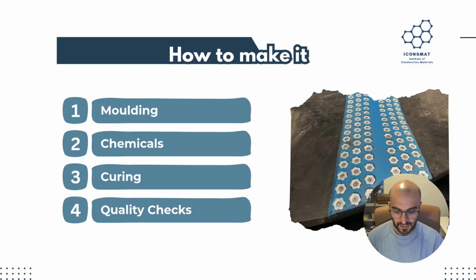Some polyurethane samples, especially the one that I've used, started to generate CO2 gas, and because of the viscosity levels of that liquid, that generated gas was entrapped inside the sample, resulting in a lower tensile strength. So, ideally, we want to have a vacuum chamber where the curing happens. There are other notes in the scientific papers where heat curing is recommended because it improves the mechanical strength and properties of polyurethane samples, let's say between temperatures of 70 to 90 degrees. Most of the literature would suggest that the highest tensile strength is achieved when samples are cured between 70 to 90 Celsius degrees. Then we move on to the quality checks.